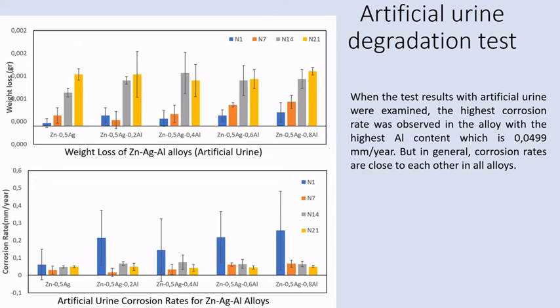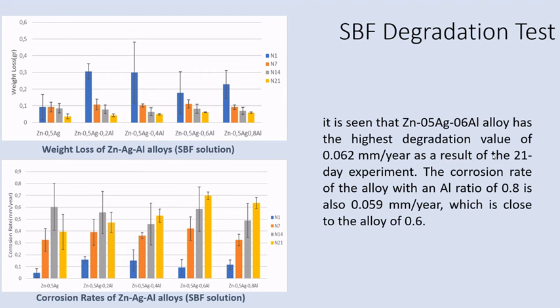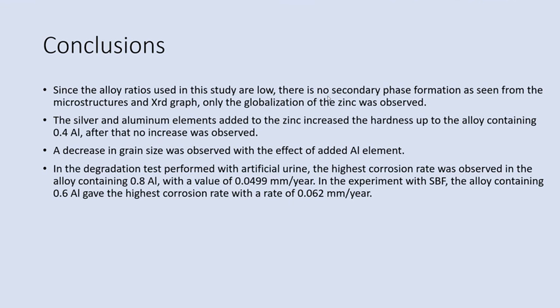And here you can see the degradation test carried out with artificial urine. The one with the highest aluminium, which is 0.8, has the highest corrosion rate, which is 0.0499 millimeters per year. But in general, corrosion rates of all alloys are close to each other. When it comes to the degradation carried out with synthetic body fluid, the one with 0.6 aluminium has the highest degradation value, which is 0.062 millimeters per year.